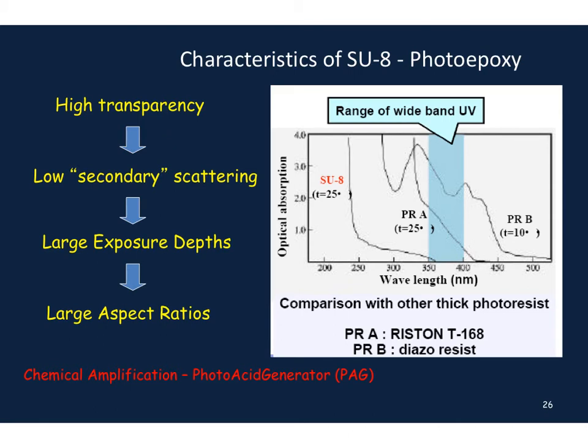So this was really fundamental because it allows us now to do up to 1 millimeter thick features, whereas most photoresists cannot do much better than 20 microns, which was a huge problem for microfluidics at the outset, until IBM invented this SU8 photoepoxy in the late 90s. It is a negative photoresist, but it's a photocurable epoxy. And the UV light causes a photochemical release of an acid, which forms this insoluble polyether network, and it's really preferred for microfluidics today. And it's possible with this stuff to get 10-to-1 height to width ratios.